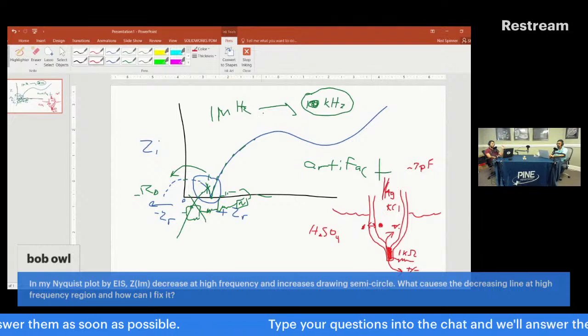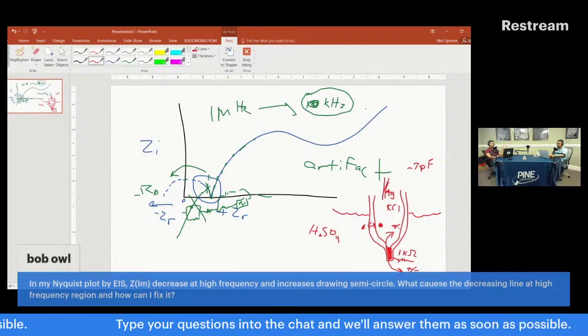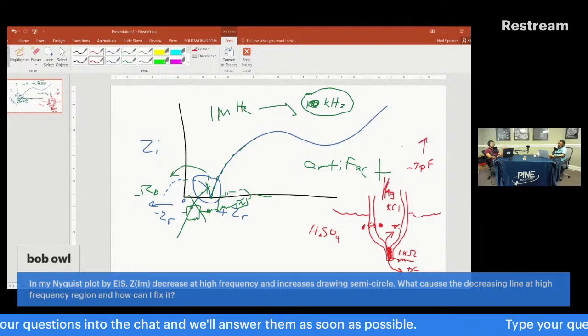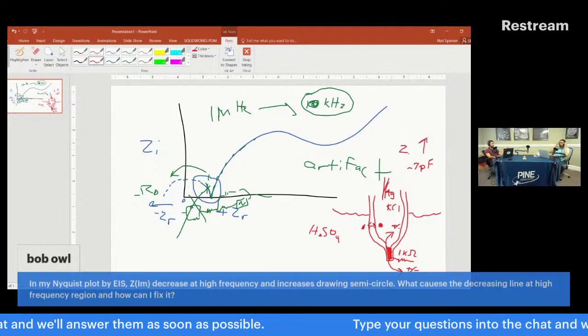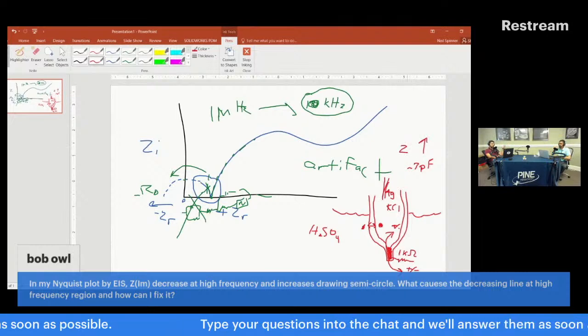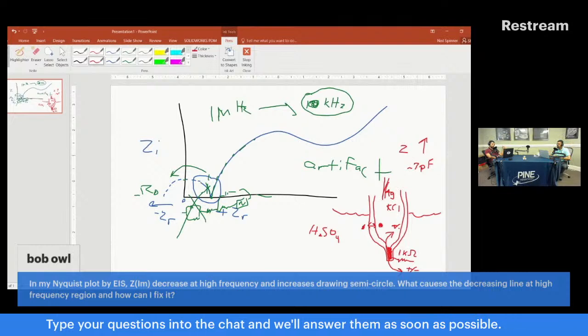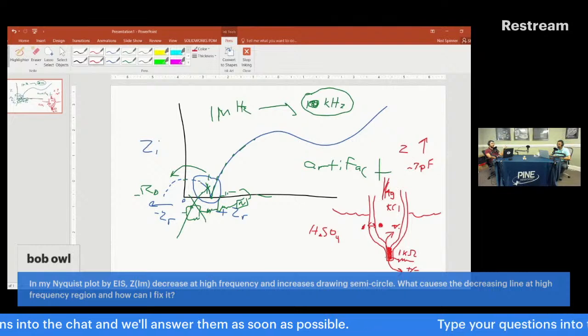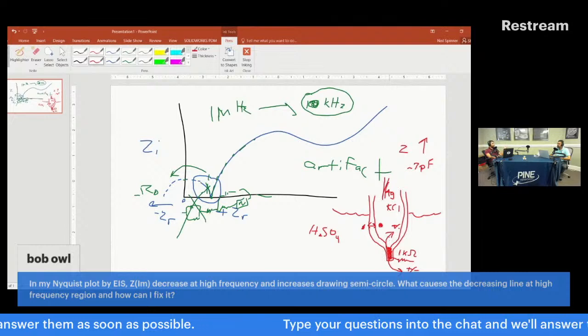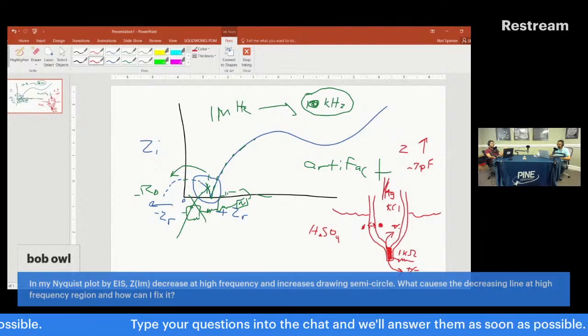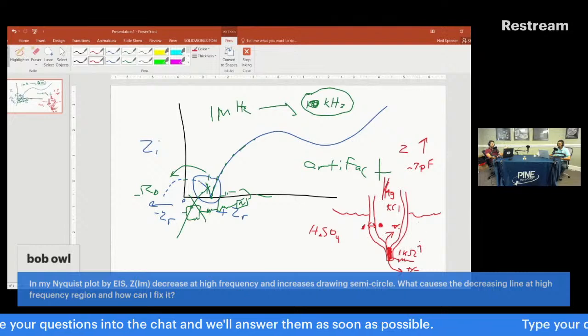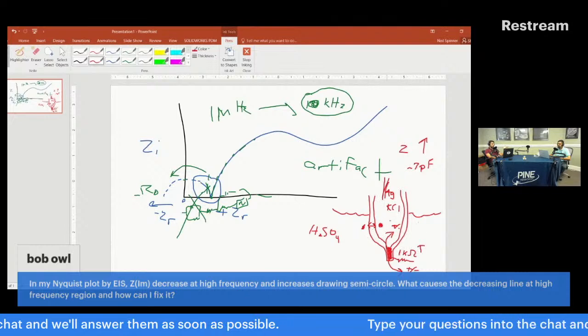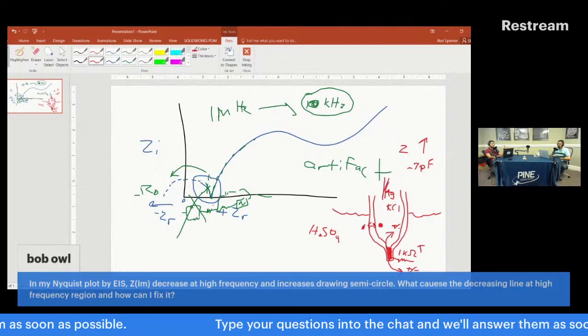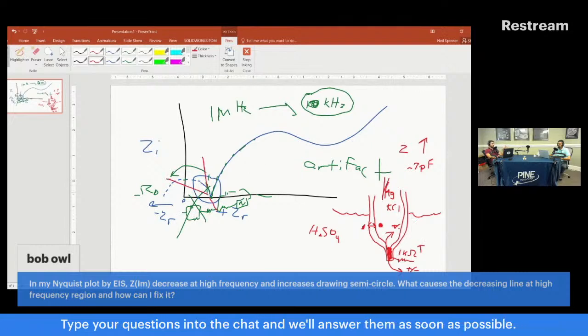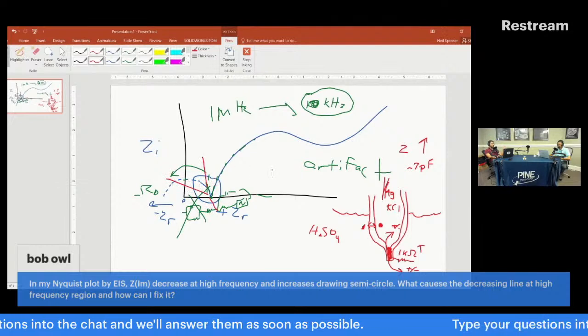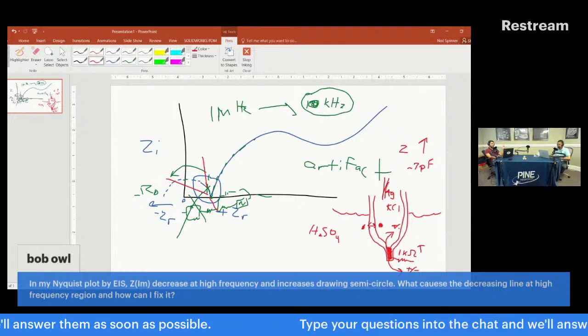Eventually, the frequency drops to 1 kilohertz, 10 kilohertz, 100 kilohertz. The impedance of this intrinsic glass capacitance goes up, and eventually it's higher than 1 kilo ohm, and then the potentiostat reverts to the appropriate pathway, which is through the frit. So this is why blocked frits are more of a problem, because it needs a pathway, and if this impedance goes up, it's going to use the glass more, and that's bad because there's no communication. That's why you have this odd behavior. Sometimes it goes down, sometimes it goes this way. You'll have strange behavior, but it's an artifact. It's not real, because it's not an actual connection. It's going through the glass.